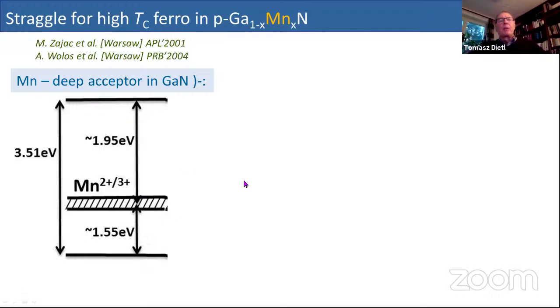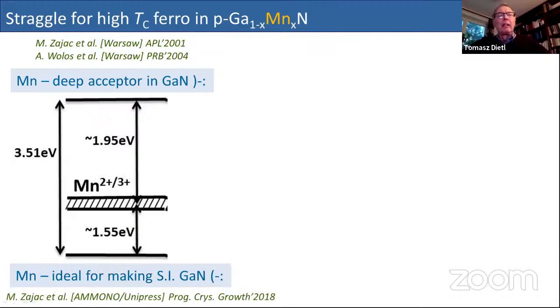Because it's such a deep acceptor, we do not see too many carriers at normal temperatures because, of course, the activation energy is very, very large. So it's very disappointing that actually we do not have any carriers at room temperature, and carriers which could be, for instance, from oxygen donors or silicon donors are trapped by this manganese, so it's a very high resistivity material. And this is actually very interesting for growers of gallium nitride, because for many devices like optical devices or high power amplifiers, you need a substrate which is semi-insulating.